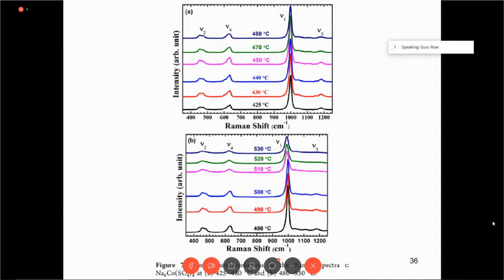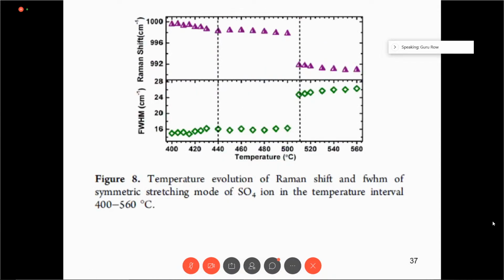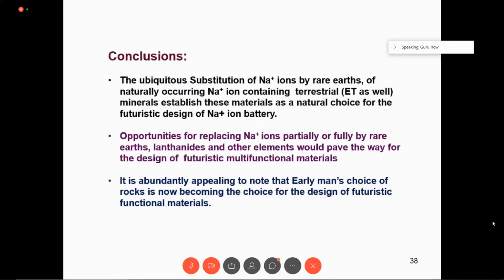And as a consequence, sodium ions are very free to move about. And therefore, we have a superionic conducting material that gets generated. We see that temperature evolution in the full width at half maximum of these stretching frequencies. And you see that these 3 phase transitions very clearly suggest the formation of this material. So with that, I come to the conclusion of the talk.